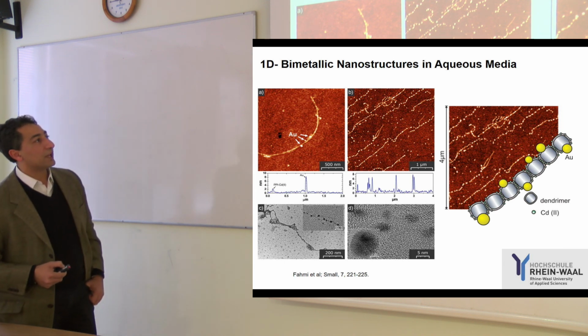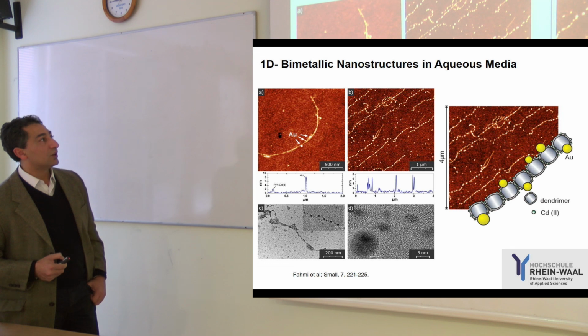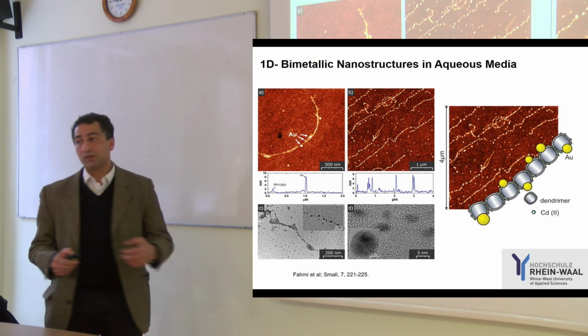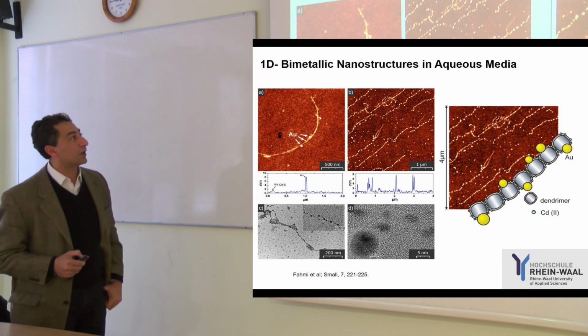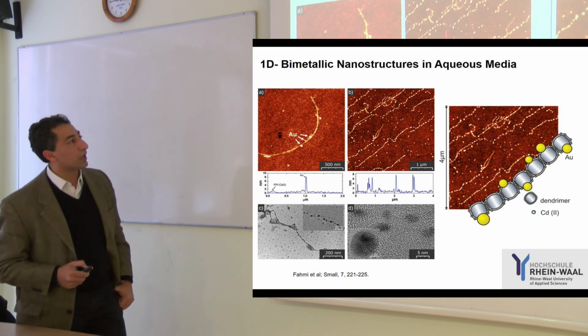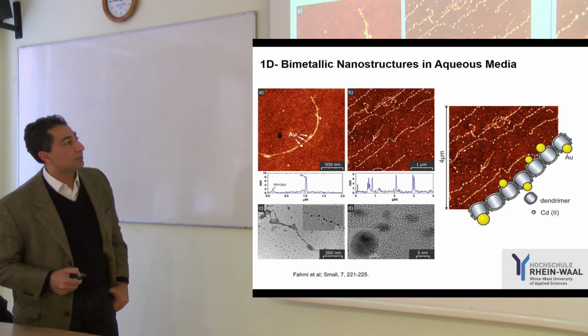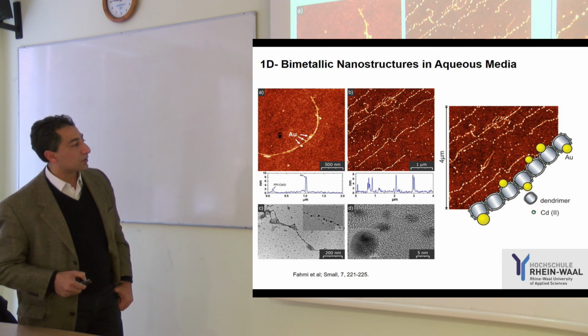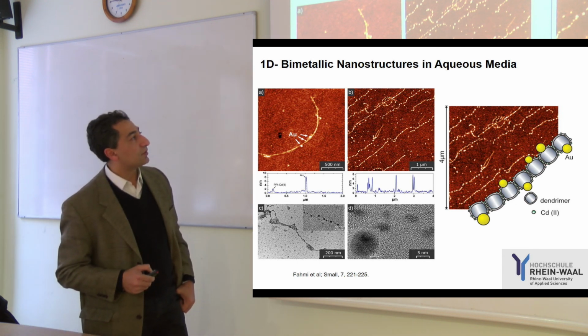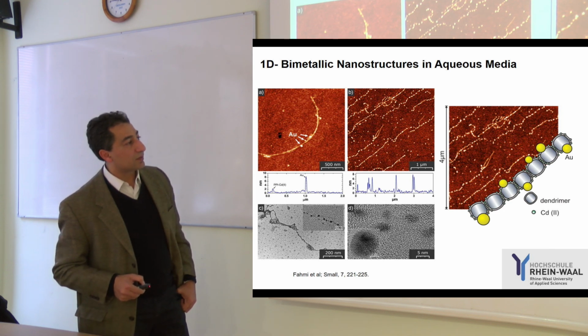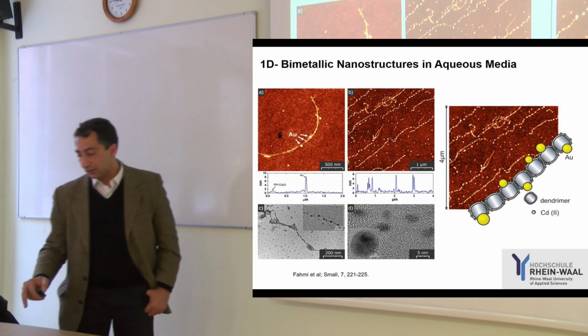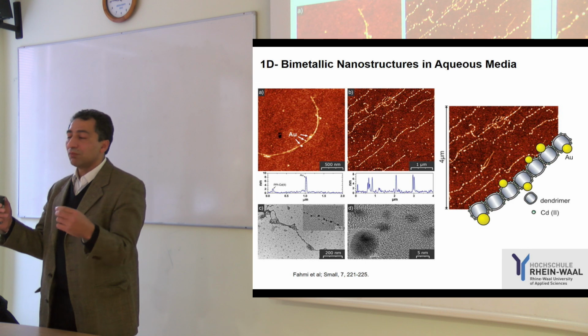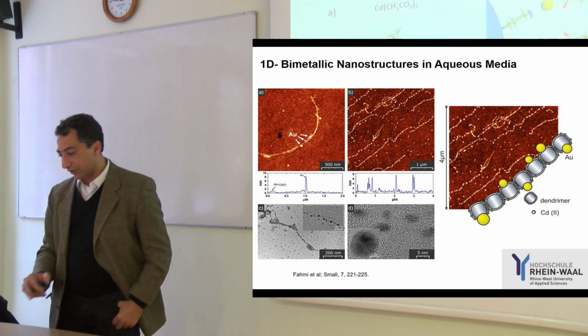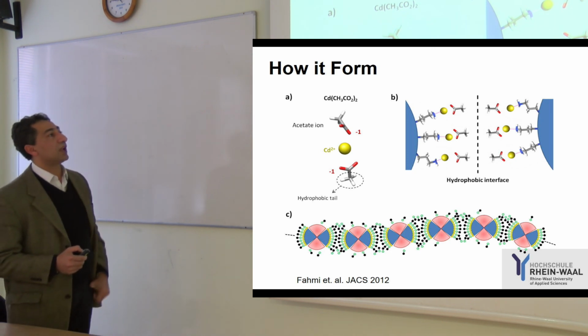After a while, we thought: we have fiber based on one metallic structure, and we would like to produce fiber using bimetallic structures, so that we can have two different types of metal in one fiber. We're using the first fiber as a scaffold for the second. In this case, we have gold, and we managed to put the gold building block or nanoparticle along the fiber in a discrete manner, as you see here from the high resolution transmission electron microscope or the atomic force microscope image. We have the first metallic structure inside here, and after that we put the other metal in. At the end of the day, we managed to make nanofiber using dendrimers with two different types of metal structure on it. Of course, we like to work out more about the mechanism.